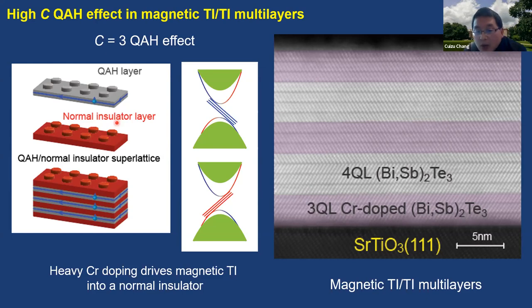So in our experiment, the idea we used is, we know that when you introduce chromium or vanadium in the bismuth antimony telluride, it will reduce the spin orbit coupling. If heavily doped, it will drive the topological insulator to a normal insulator layer. So we're using this very heavily chromium doped topological insulator layer as the normal insulator to connect the C equals one quantum anomalous Hall layers to realize the high Chern number quantum anomalous Hall effect. So this is the TEM image we grew.